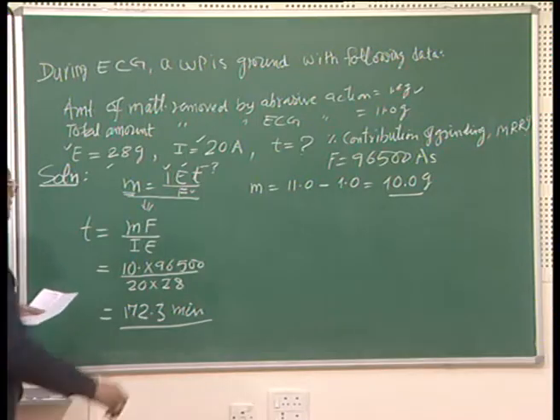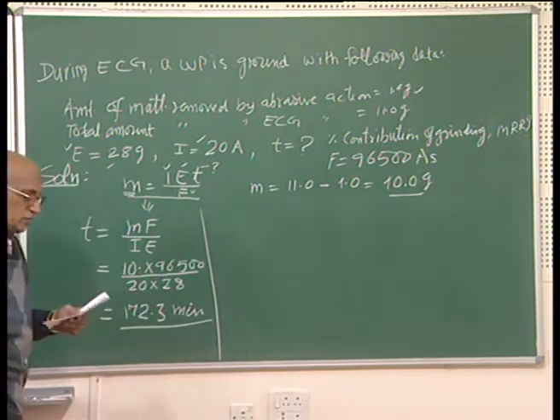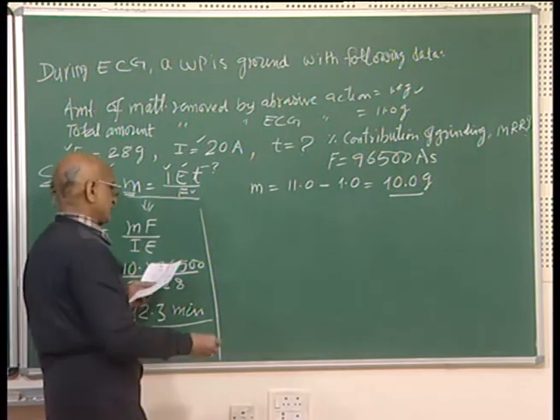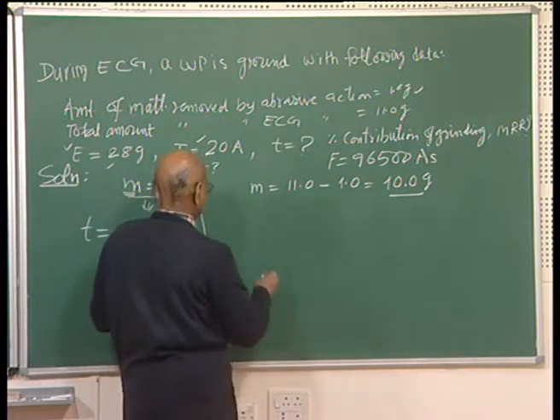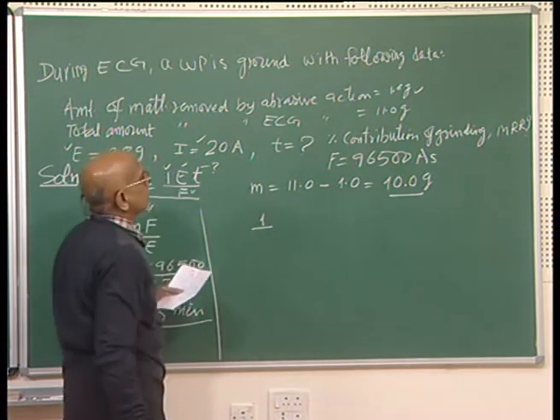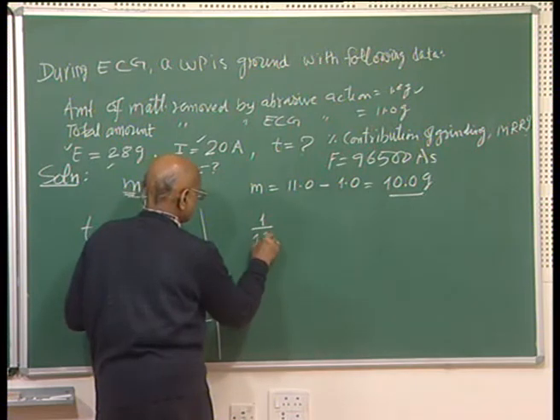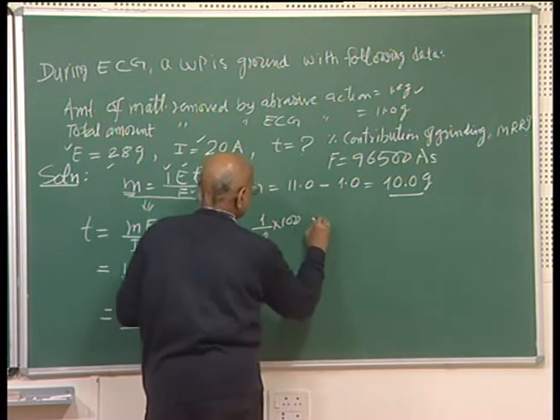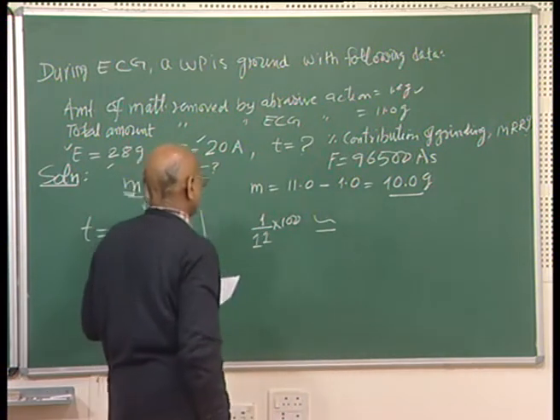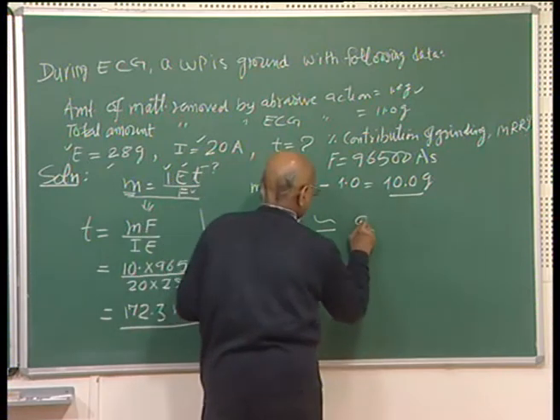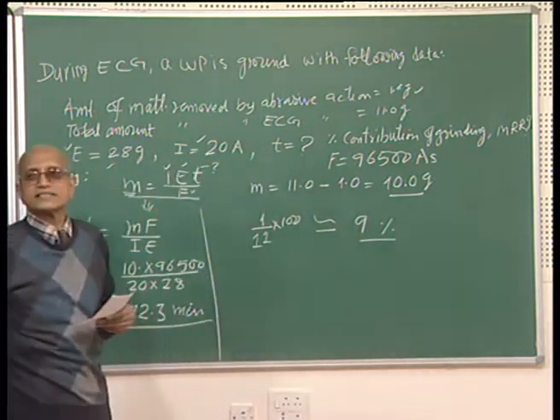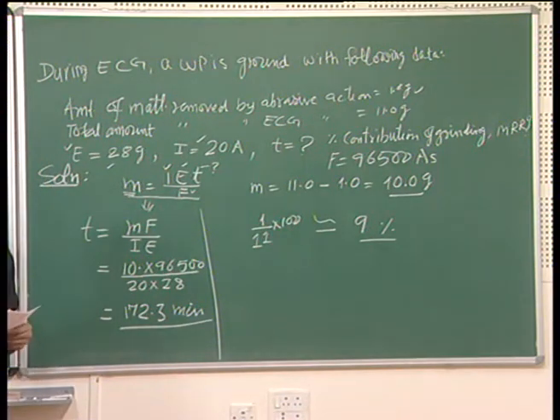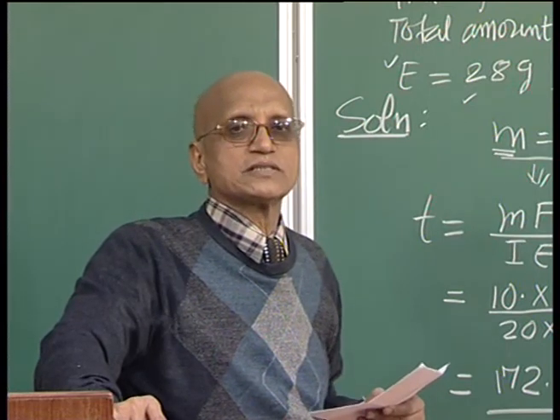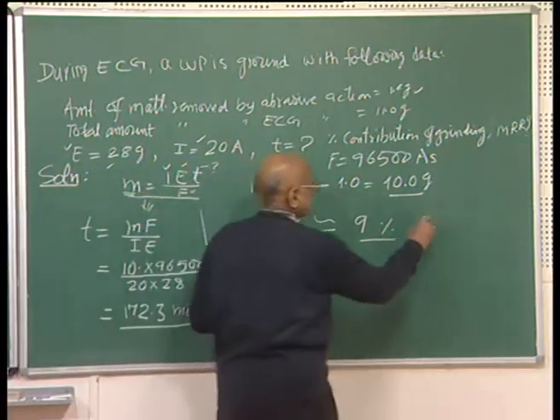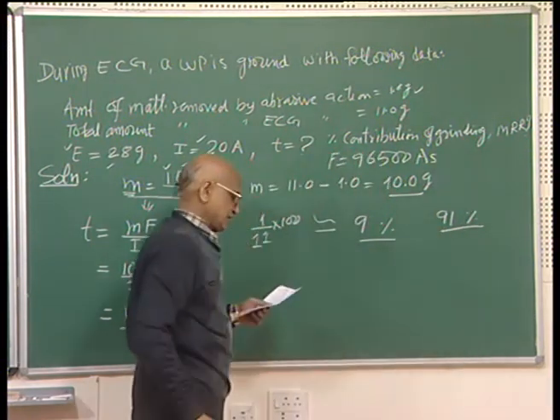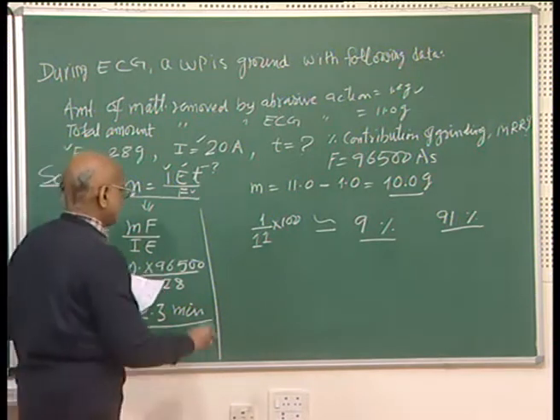Now, the next question is, what is the contribution of grinding alone in percentage? So, we can write here that it was 1 gram divided by 11, into 100. So, you can calculate that it will come out to be approximately 9%. So, it indicates that the grinding contribution in this particular case is just 9%, while the electrochemical dissolution contribution comes out to be 91%, which is quite high. Now, we can also calculate the material removal rate.